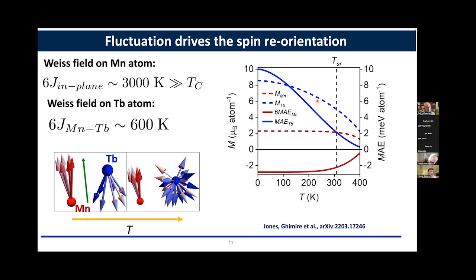Now, we also calculated the magnetic anisotropy energy based on these manganese moments, as well as by measuring the magnetization behaviors as a function of temperature. These dotted lines are basically the same ones that I showed you in the previous slide. These are just the magnetic moments of manganese and terbium. These solid lines are the magnetic anisotropy energy. This blue one is for terbium, and the red one is for the manganese atom.